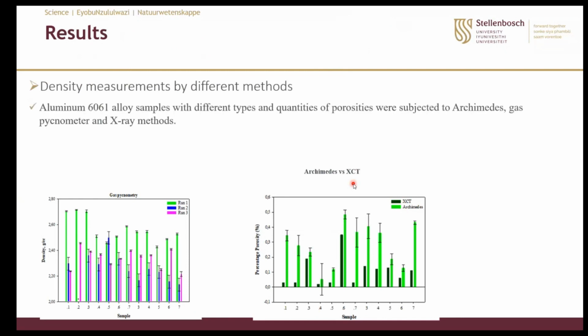And then what I have done so far with my other team is we looked at the measurement of porosity with different methods. It was an aluminum sample, a 6061 type of alloy, which we used to measure porosity through Archimedes, the gas pycnometer, and a computed tomography method. This was motivated by the fact that even though computed tomography is a very good non-destructive testing method, it takes long and is quite expensive. On the other hand, the Archimedes method is quite affordable and easy to use. So we took a number of measurements.